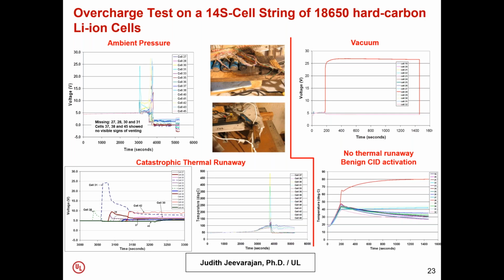And when we did the same test under a vacuum condition, we found that there is benign CID activation of every single cell. So the heat dissipation that occurs in an ambient condition versus a vacuum condition really changes whether that CID activation results in a catastrophic failure or not.